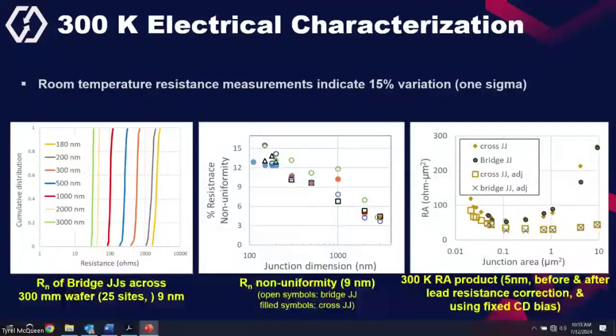because we measured 25 sites distributed across the entire wafer. The main point of doing this 300 millimeter fabrication is that we should get a tight distribution in terms of all the parameters of the junction, whether it is CD, critical dimensions, or the electrical properties, or the low temperature characteristics. Here we see that for lower dimension junctions, we have higher non-uniformity. We are working to improve that, but for the higher dimensions, we have good non-uniformity in terms of resistances.